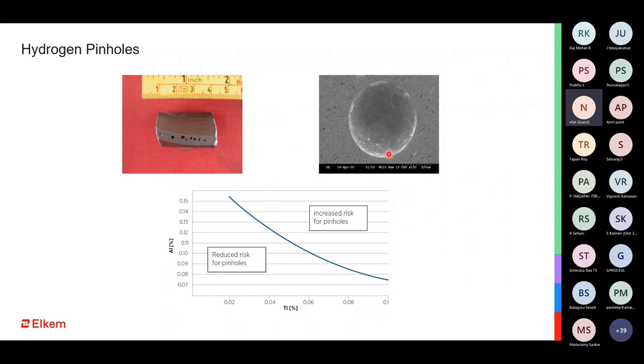This is just an indicator. You can see this is a photograph taken using a SEM, a scanning electron microscope. And this is how the inner cavity of the hydrogen pinhole appears at a higher magnification and at a depth of focus. You can see the black shiny part inside, and you can also see some amount of graphite being depleted around it. And that is a clear indicator of a hydrogen pinhole.